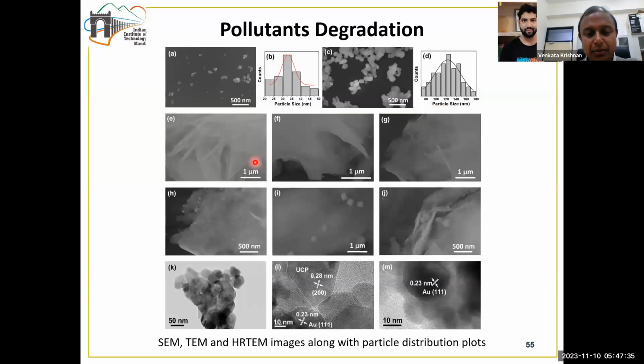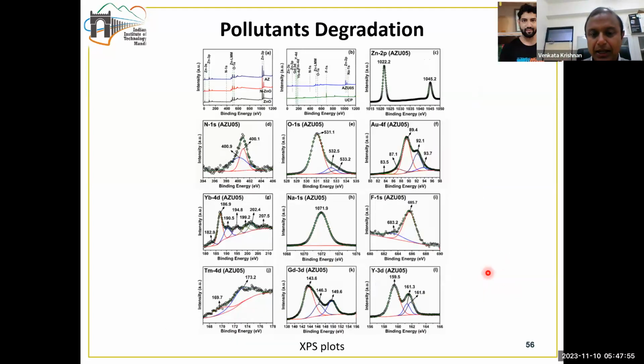Then we did the morphological study using SEM analysis and also the TEM analysis, which indicated what type of material is being formed. So with the upconversion nanoparticles, it's a core shell type of structure. The N-doped ZnO, it's a sheet type of structure. And finally, the gold nanoparticles, these are again small spherical structures, which are decorated onto this material. Then we did a detailed XPS analysis to understand more information about the different surface electronic properties of this material.